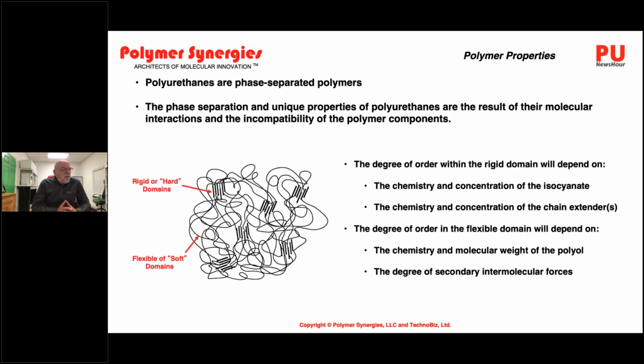Polyurethanes, of course, are phase-separated polymers. This phase separation and the unique properties of polyurethanes are the result of the molecular interactions and the incompatibility of the polymer components. So when we talk about the degree of order within the rigid domain, this will depend on the chemistry and the concentration of the isocyanate and the chemistry and the concentration of the chain extender. So are we using an aromatic or an aliphatic isocyanate? Are we using a diol or an amine as a chain extender? These things will affect the order of that rigid domain and the size of that rigid domain.